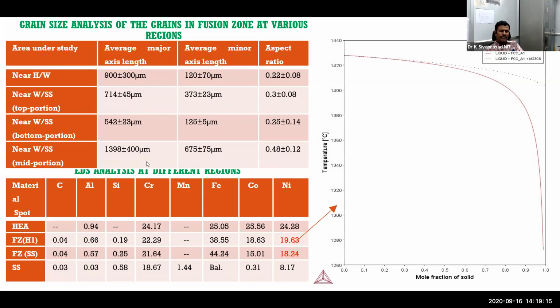This clearly explains that there is no abrupt change in values, there is a gradual variation. And similarly, elemental analysis also we have done. Here also, if you see, all the elements are not abruptly changed, only a gradual change is there. And nickel in the fusion zone, on both sides, the HA side as well as the stainless steel side, a good amount of nickel is there. So the good amount of nickel favored the structural integrity associated with this joint.